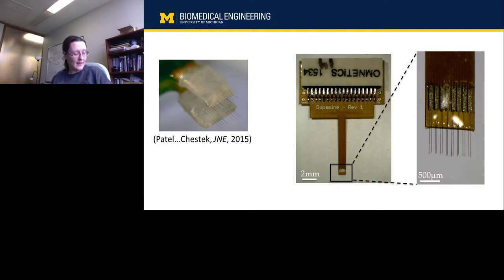And so I should say that basically the important thing is to penetrate that top layer called the pia. Once you're through the pia, you basically have your pilot hole, and it's holding the carbon fiber in place. And you can actually drive a carbon fiber all the way through a brain at that point. So it's just that first layer of penetration that's really important.